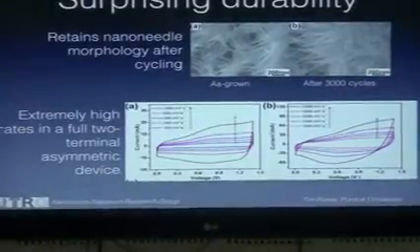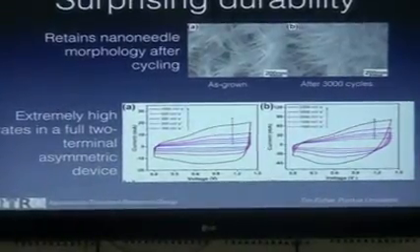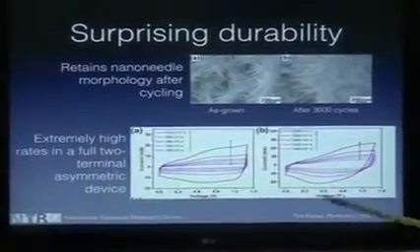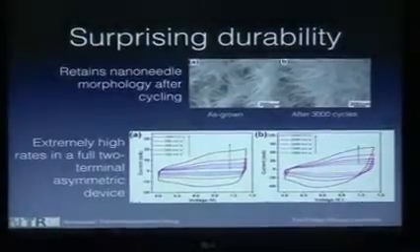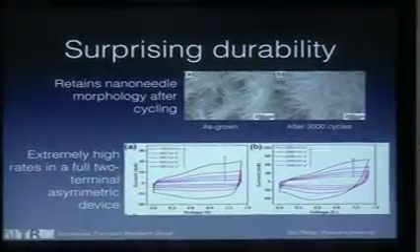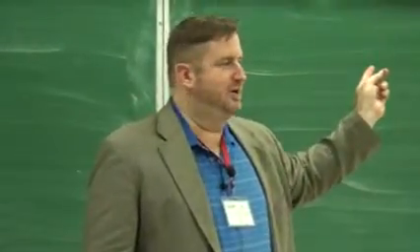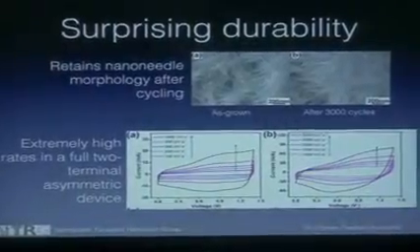Now we start to look more rectangular. And this has to do with the fact that on the carbon side, we're adding a double layer capacitor to it. We still see some redox features, right? Shoulders in the curve. But now this is really a hybrid or an asymmetric structure. I'm not sure whether you'd call it a hybrid battery supercapacitor or an asymmetric supercapacitor. It gets back to whether I want to satisfy ACS or RSC. I don't care. But the point is that I have a more rectangular type of CV curve when I make this hybridization happen.